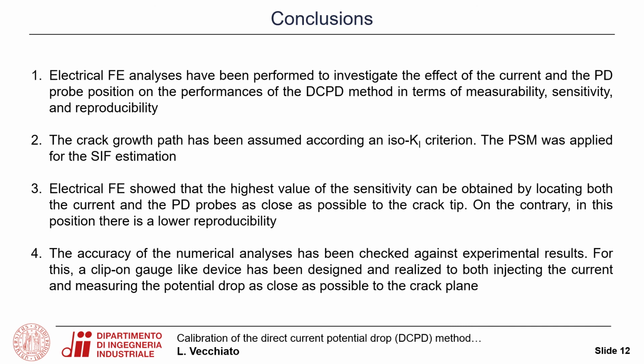Electrical finite element analysis showed that the highest value of the sensitivity can be obtained by locating both the current and the potential drop probes as close as possible to the crack tip, and on the contrary, this position leads to the lowest value of the reproducibility. At last, the accuracy of the numerical analysis has been checked against experimental results, and for doing this, a clip-on gauge-like device has been designed and realized to both inject the current and measure the potential drop as close as possible to the crack plane, the crack tip.